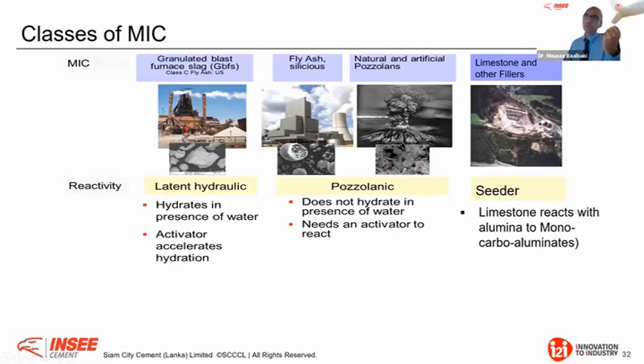Because those products, if we mix them with water only, I take slag, I mix it with water, to a certain fineness, of course, grind it. After a certain time, I will develop exactly the same hydrated product as clinker, as OPC. Therefore, this is why we call them latent hydraulic. And we can achieve some more performance by adding some activator, what you call an accelerator for hydration.